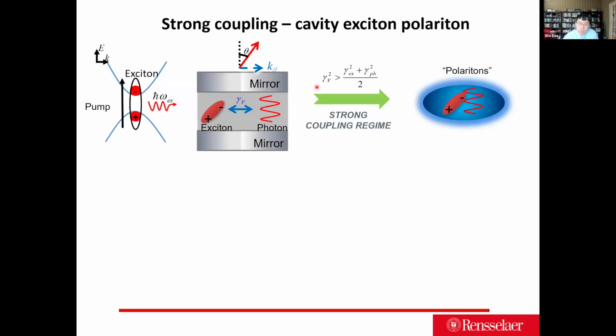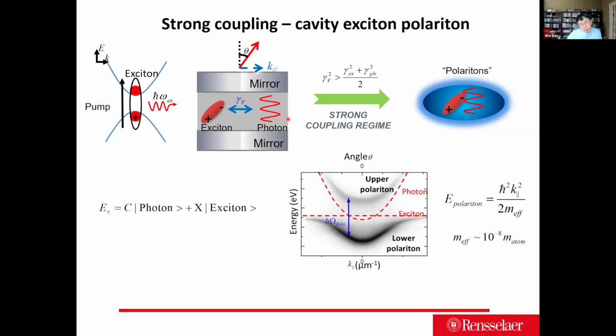So if the coupling rate between the exciton and the photon is much larger than those two loss channels, we are entering a new regime we call the strong coupling regime. Essentially, we form a new quasiparticle called the polariton inside the cavity. Another way to say it is that any photon escaping from the cavity will experience the energy states of both the previous exciton and the photon, and one can write it as a linear combination, a hybridized state. Essentially, it's the photon state with a certain portion and the exciton state in another portion.